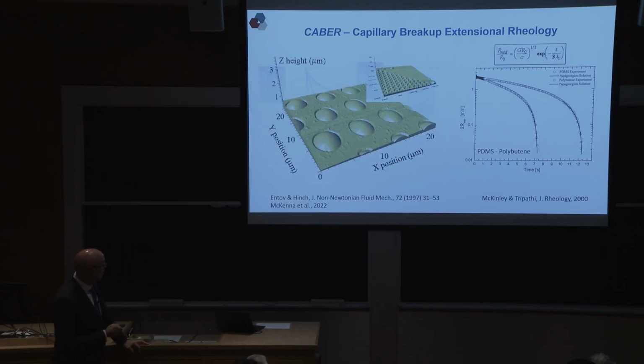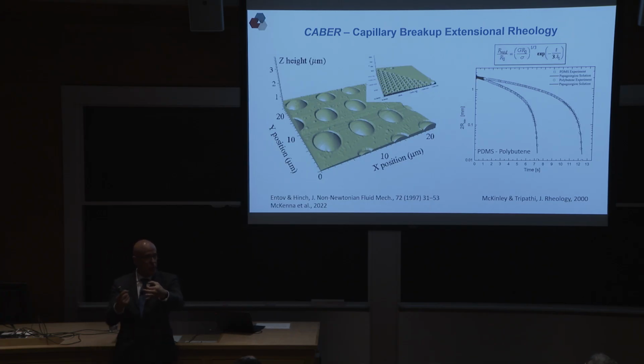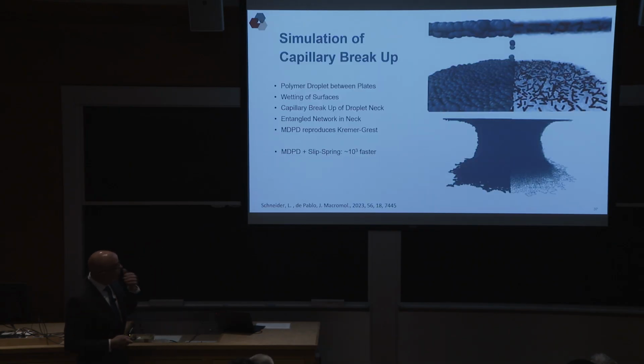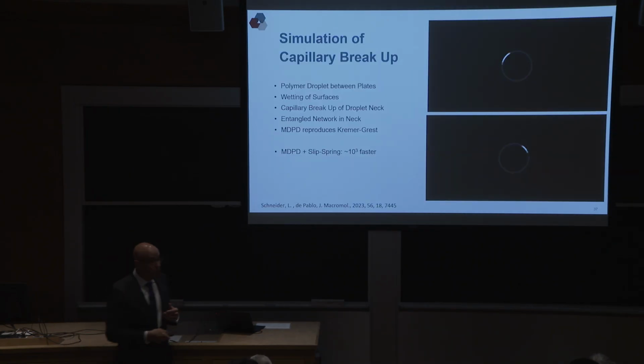Another way of doing it by a different group, that would be Greg McKenna, would be to have these thin films of polymer that he puts on the top of holes. These are nano bubbles. He blows air from the bottom. You form this little bubble, and you measure the change in curvature as a function of time for a given pressure, and you back out the rheology. Again, high throughput, because each of these can be a different sample. But you need a model that tells you what the polymer is doing to extract the rheology. So one of the things that we've done is generalize these models to interfaces and surfaces. So now the slip springs are also living on the